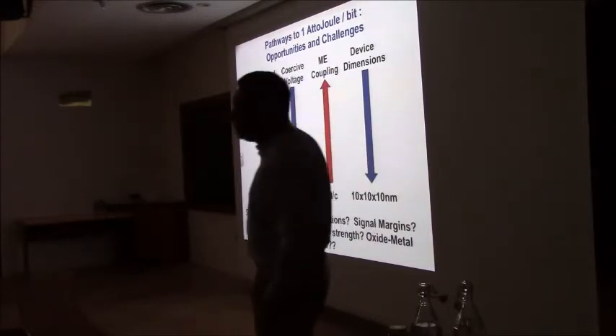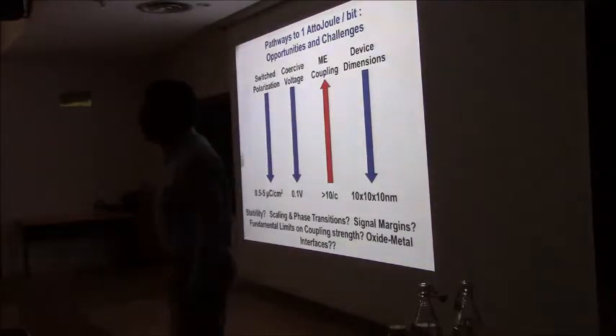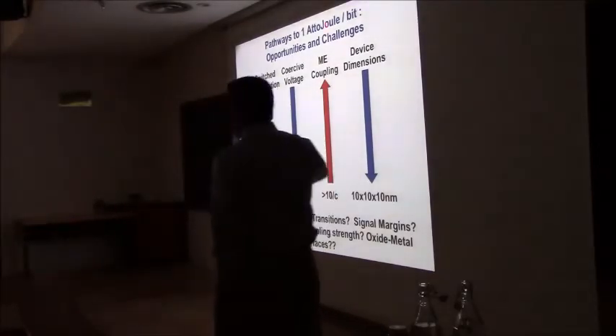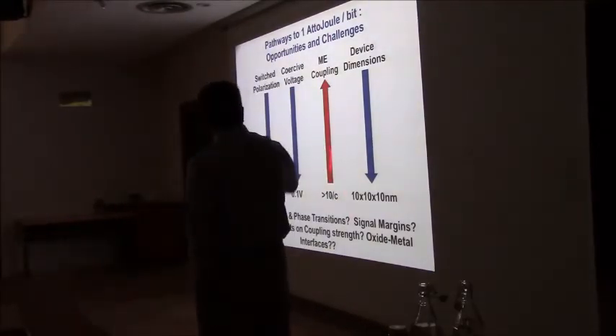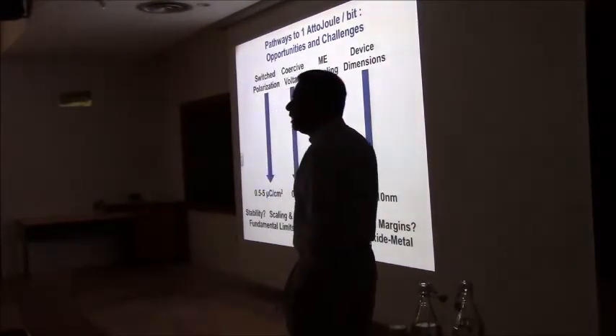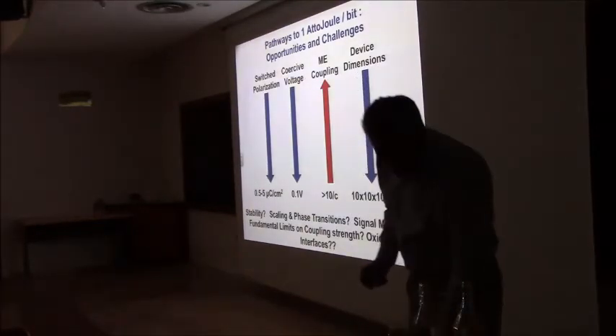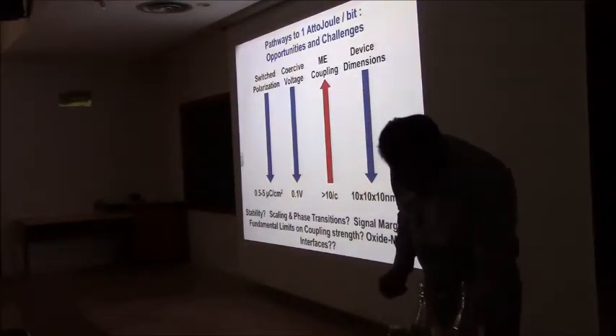The coercive voltage is by far the toughest one. You want to have 100 millivolts, actually even lower, because I should be looking at the maximum voltage, so that's an issue. Magnetoelectric coupling should be high, which is why it's red and pointing the other direction. Of course, device dimension, we're assuming something that will be of the order of 10 by 10 nanometers. So what are the big questions?